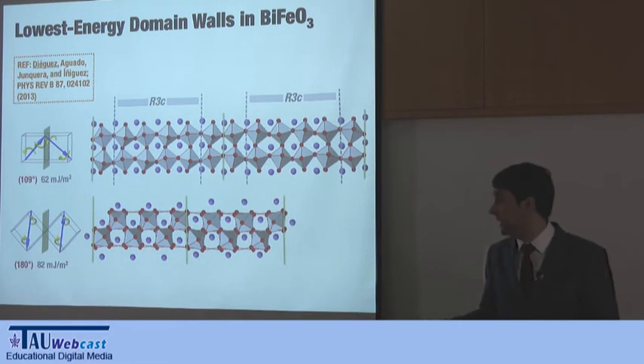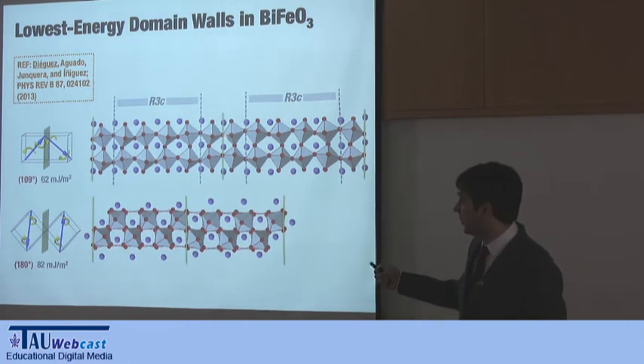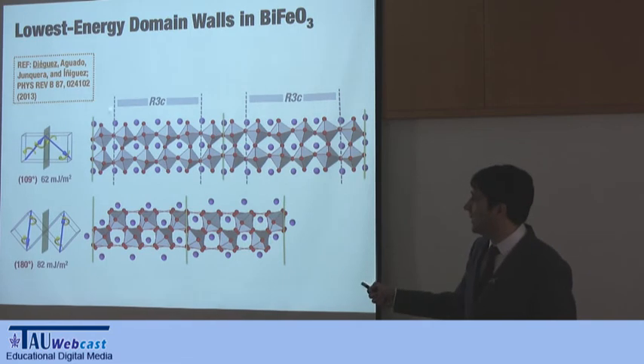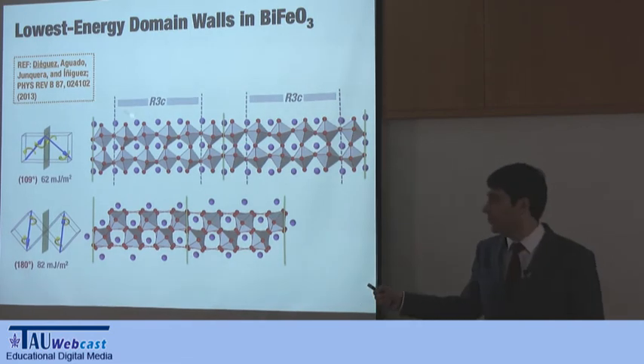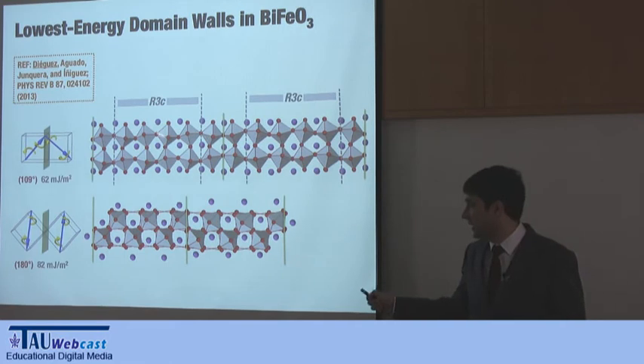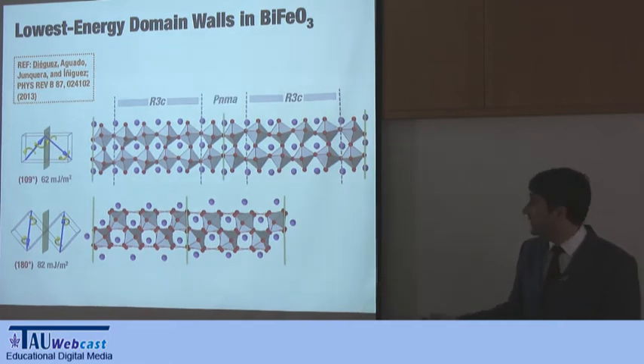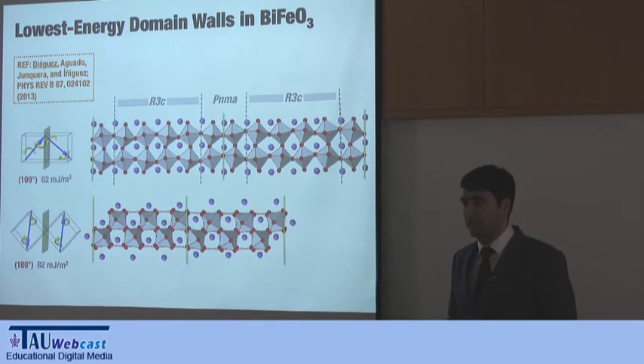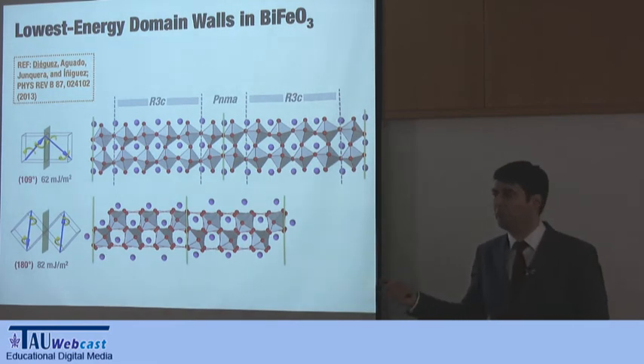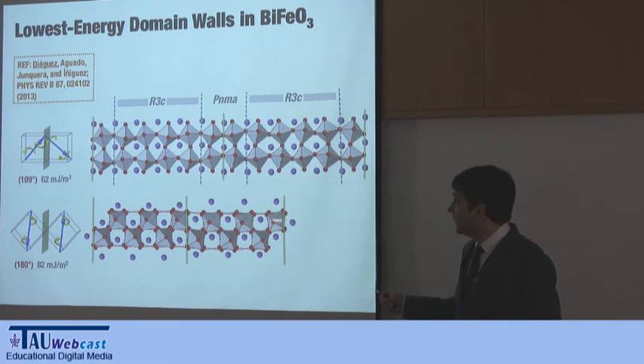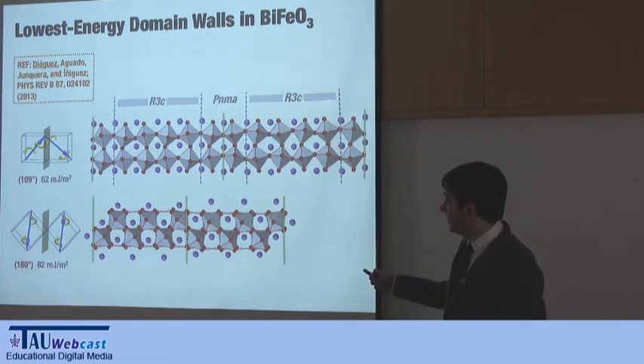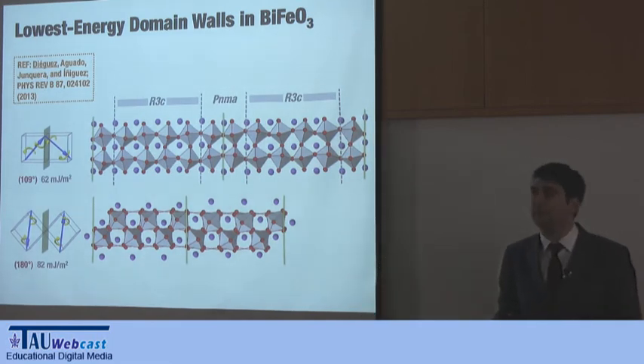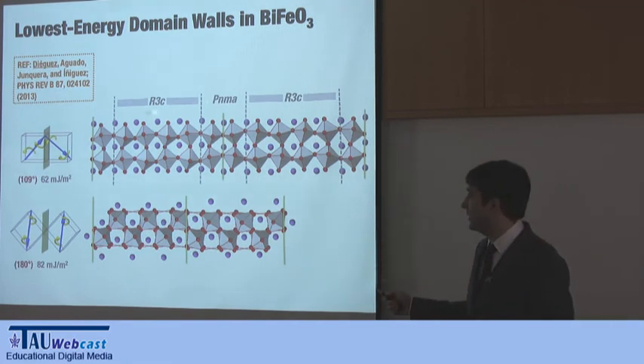It has 120 atoms. There are one domain that is replicated. There are two domains that are equivalent, and what we see is in the middle of the domain, you get the ground state. This is the bulk. This is how the solid wants to behave. And in the domain wall, you get the phase at high pressure. So what you get here is that the octahedral network is very little distorted because it can accommodate a mix of two phases.